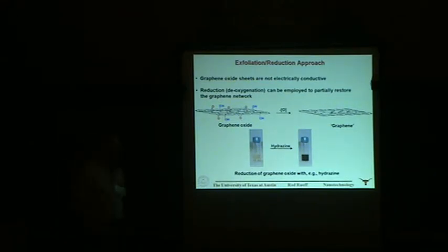Is that a pretty accurate figure? That's a great question. It's not a stoichiometric compound. No, this is pretty typical, but these numbers move depending on who does the synthesis and exactly what methods. Within what range, percentage-wise, 10%? 10 to 15%. Yeah. It depends on the starting graphite, on which oxidant is used, on the scale of the synthesis, and things like that.